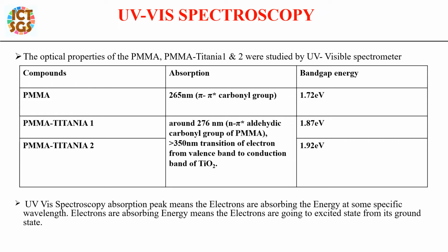A UV visible spectroscopy absorption peak means the electrons are absorbing energy at some specific wavelength. The electrons absorbing energy means the electrons are going from the ground state to an excited state. The band gap energies of PMMA and PMMA-Titania 1 and 2 are 1.72 electron volt, 1.87 electron volt and 1.92 electron volt. These values are less than 2 electron volt, which indicates the polymer and nanocomposites are semiconductors, which is confirmed by the electrochemical studies.